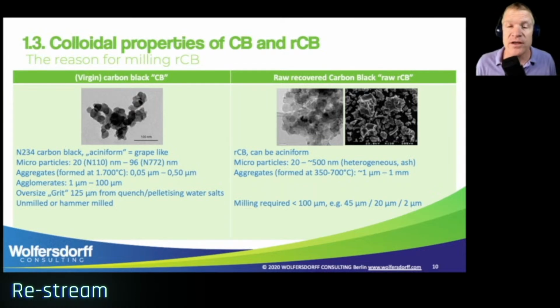We also have aggregates. However, here in the pyrolysis, we don't have the high temperatures of the carbon black manufacturing reactor. We have temperatures maybe between 350 and on the upper side 700 degrees Celsius. Now we have a very large aggregate size between about 1 micron and 1 millimeter, or even several millimeters. So there is a need of milling for recovered carbon black. And the milling should in any case be below 100 micron. It's very difficult to have any performance in rubbers and plastics for recovered carbon black that is unmilled and might be much bigger than 100 micron. A really good or standard quality recovered carbon black might be below 45 micron. For plastics and coloring, I really recommend finer milling, which could be 20 micron.